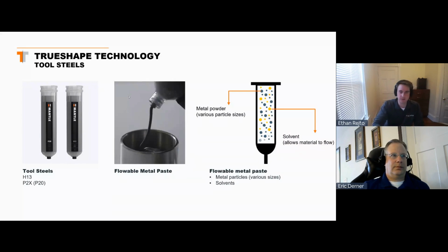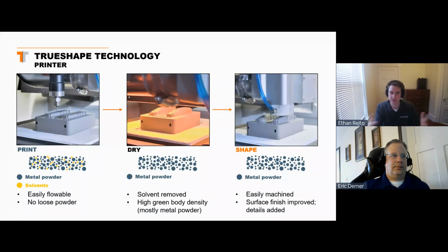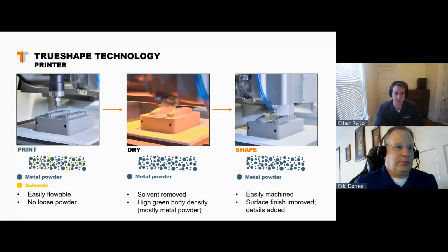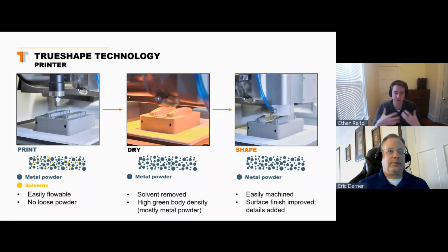So the first step in our process, this is all happening within our printer, is to print. We're printing this metal paste. It's flowable. We don't even actually have to heat it. It's viscous enough to just be extruded through a nozzle. And we're extruding this combination of metal powder mixed with these solvents. Again, no loose powder in the process.